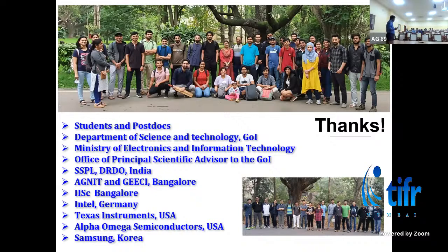Right. So, yeah, there may be other methods as well that people will discover tomorrow. But the fundamental underlying principle is the same. You basically get fluorine, and again, in that case, we found that the fluorine works only if you have the sulfur vacancies, right? So just introducing fluorine does not work. You have certain defect states, you bring another kind of interstitial, right? And then you bring a particular kind of metal, and they hybridize to form that kind of state, which allows you better electron injection.